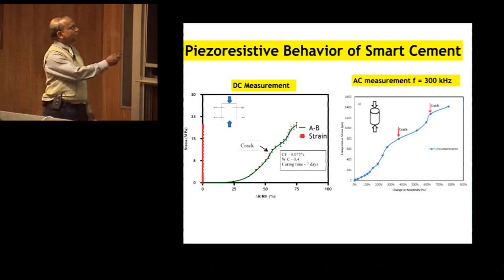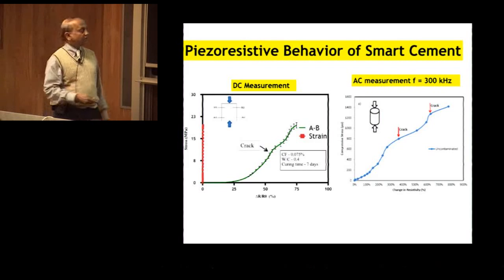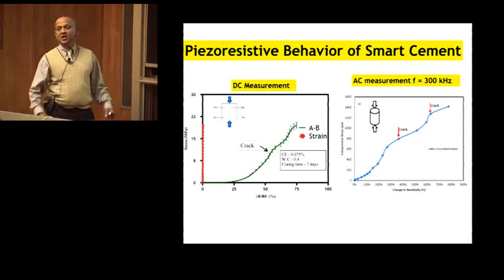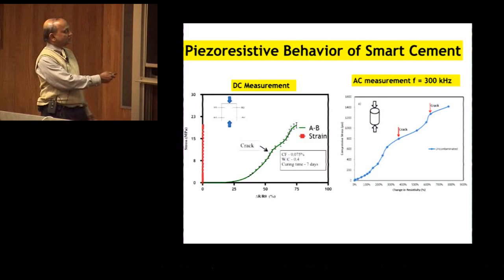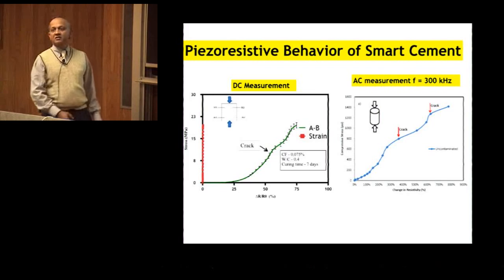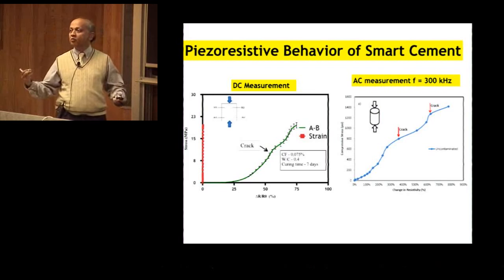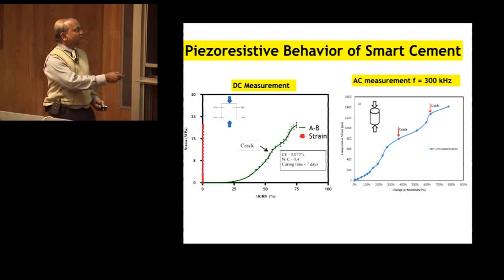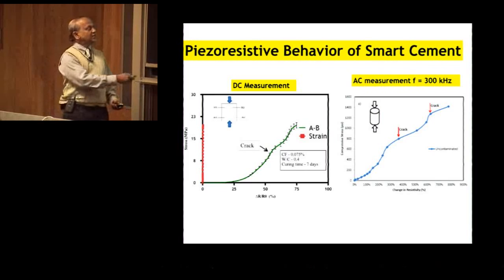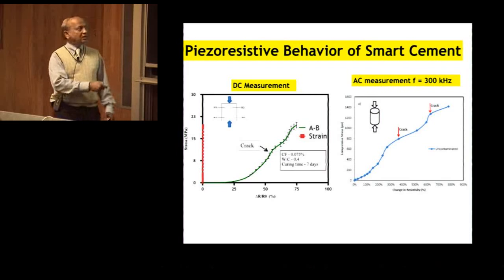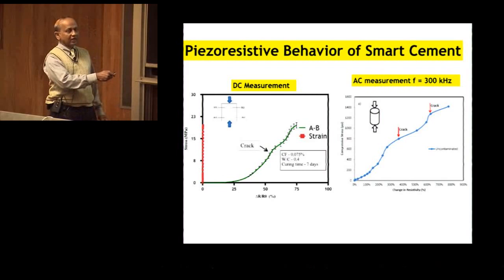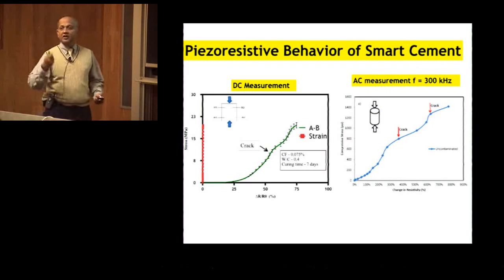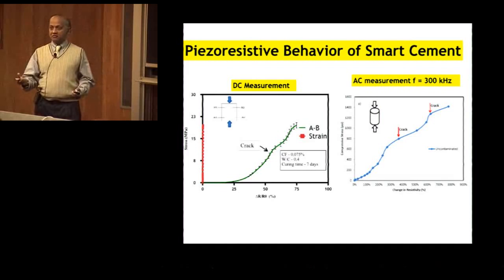And we moved from DC measurements, which we started with, to now doing AC measurements. Same material. Look at the numbers. This was in the 80s, now this is in the 500 to 600. They have become so sensitive. Why? It's very clear. We have taken out the contact resistance, and this is the bulk resistance change. And when you load it, the material deforms, and when there's a crack, the resistivity changes a lot. And from these changes, we can identify the condition in the cement.